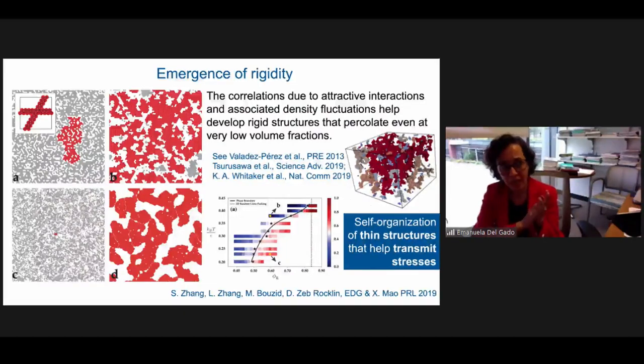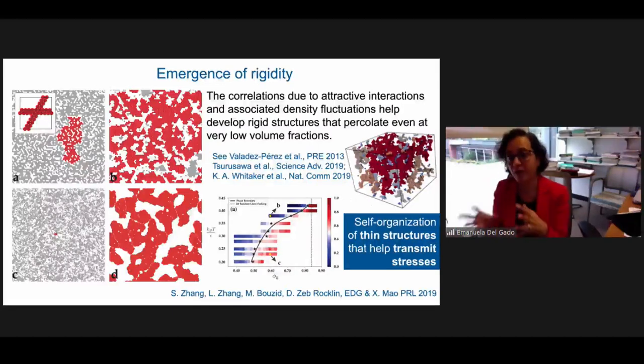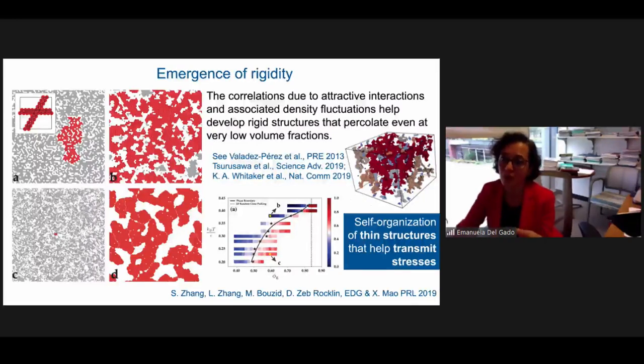The idea is that because of all these microscopic processes, equilibrium and non-equilibrium, that initiate the gelation, and then the frustration that emerges as some kind of collective process, the connection between these rigid structures and the formation of the rigid structures themselves must come from very strongly spatially and temporally correlated processes that come from density fluctuations in the system, microscopic dynamics that is spatio-temporally correlated, and so on. And so we tested this idea, first developing a lattice model for correlated rigidity perturbation, and then we tested it through molecular dynamics simulations.